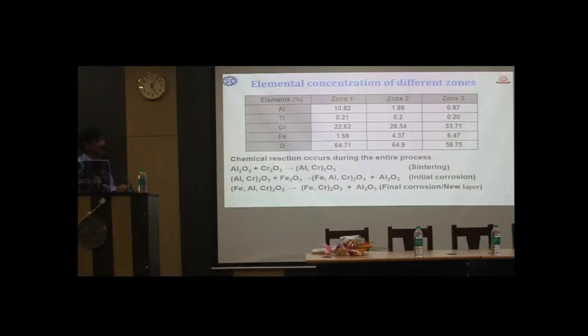So then zone 1, zone 2, zone 3 from point analysis of the individual grain. Zone 1 is towards the unreacted refractory, and there the atomic concentration percentage is 10.82, the aluminum concentration is more. When you move towards the glass, it is 1.98 in the middle, and near the glass it is only 0.87. That means aluminum is continuously moving towards the glass. Now the interesting thing is iron oxide. Near the glass region, it is 6.47, zone 2, 4.37 and 1.66.